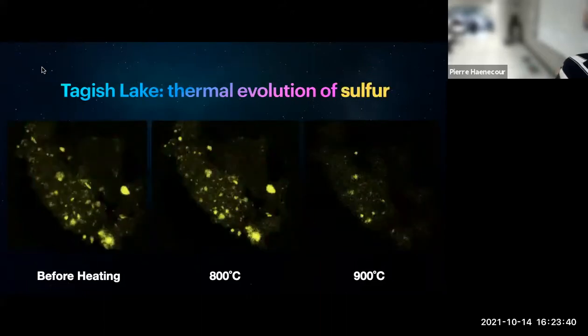If we look at sulfide, here I'm showing you in yellow the sulfur map. All those white spots are most likely iron sulfide. You can see that as you heat the sample, especially after long exposure at 900 degrees, you lose most of the iron sulfide, showing that most of the iron is gone and the sulfur is basically just vaporized. It's probably just left in the vacuum. So you basically lost it from the sample.